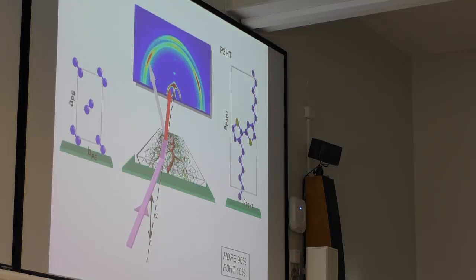Here's another example where we were looking at polymer blends, roughly 10 years ago, which was polyethylene, which has a unit cell which looks like this, where the chain now is coming out of the plane, out of the screen. Whereas here you see a polyhexyl thiophene, and here the main polymer chain is clearly running in this direction. Right, so in both cases, with the orientations I have shown here, the polymer backbone is parallel to the substrate.